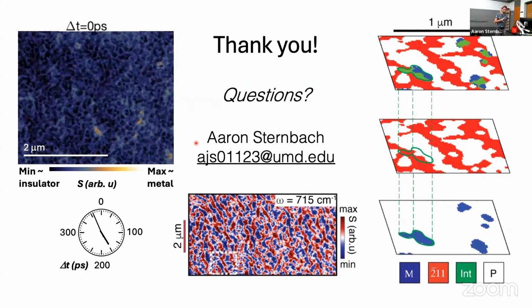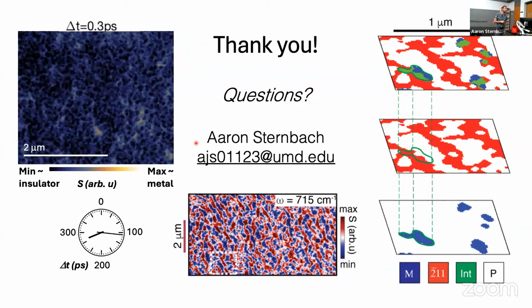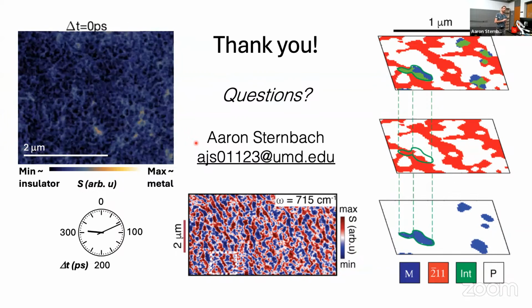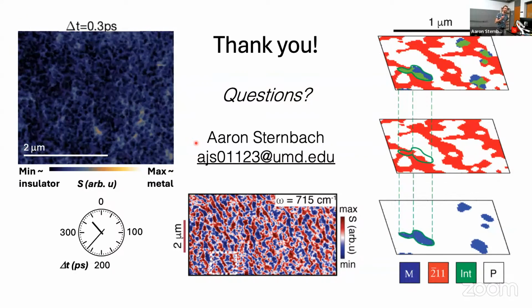No, there are reports addressing this. I'm not sure if it's published, but I had a look at a paper recently that was dealing with exactly this, trying to do sub 15 femtosecond spectroscopy to look at this regime. And it's certainly an interesting regime. There's also reports saying this 60 femtosecond phonon bottleneck could vary as a function of location, strain field, and so on. So there's always room to debate.